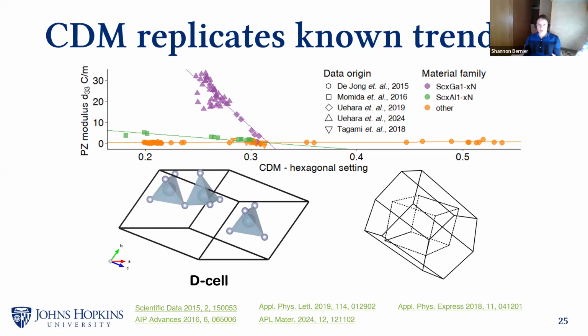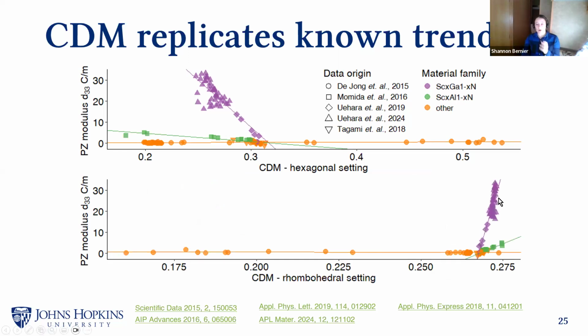So if you were to use this example and switch to a different unit cell choice, then you could not talk about the C to A lattice ratio because, A, they're no longer oriented in the same direction, and so they're no longer oriented along the direction of the cation anion separation that's important, but also the C and the A lattice parameters are the same in this unit cell. So if you apply the CDM with this redefinition, you actually can reproduce the grouping, although the trend goes in a different direction.